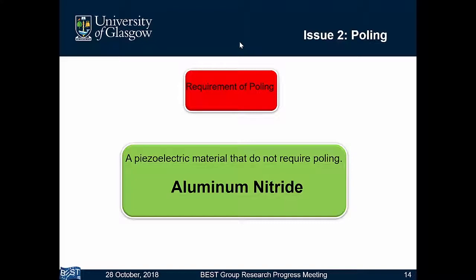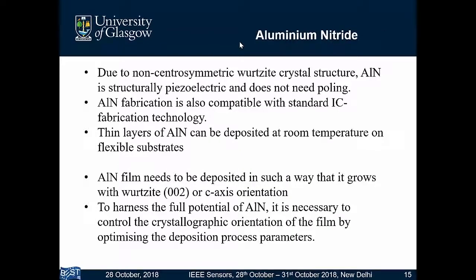By certain direction I mean that when we deposit aluminum nitride by sputtering, it can deposit in random crystal orientations, such as 001 and 100, but the orientation which we want is just 002. So 002 gives the piezoelectric response. For that, extensive process optimization has to be carried out,